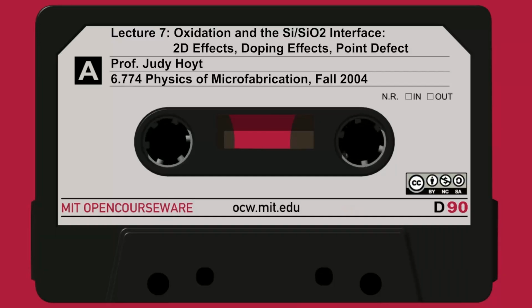Vacancies at the surface are being consumed, presumably because we need space for that oxide to move, to push around a little bit. And so consuming a vacancy will help you find extra space, essentially, at the interface. So I consume a vacancy on the left, I form SiO2, and on the right side I also create a certain number of interstitials, plus stress, of course.